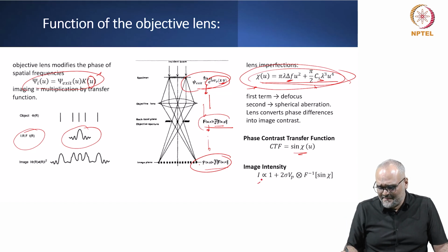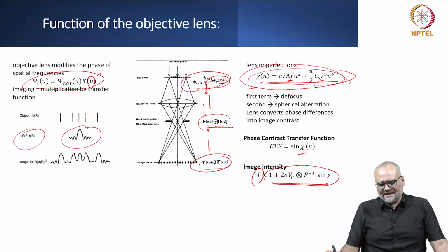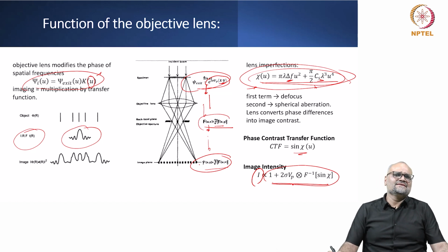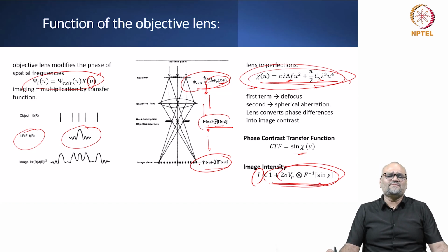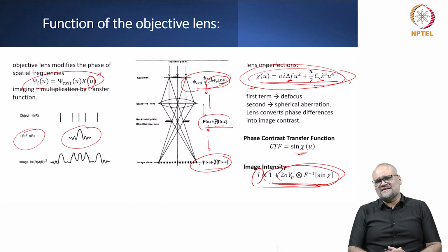So the image intensity I record in an HREM micrograph is proportional to this kind of a term, and what we have done here is simply take the linear imaging theory simplifications and write a simple mathematical expansion, a summation of a unity plus the convolution of the complex number that we had here. So the image intensity that is recorded for very thin specimens can be represented this way. This is what you get in an HREM micrograph.